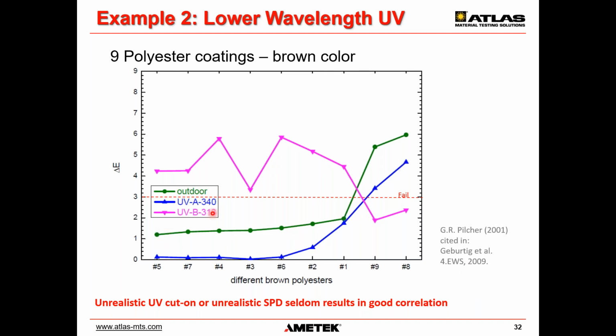The outdoor data is green, the UVA 340 is blue, and the UVB 313, high energy, low wavelength photon UV fluorescent lamps, is in violet here, in pink. And now look at the data. Only coating number 1 produces the same magnitude of change. The UVB 313 lamps in pink produces completely different rankings and magnitudes. The 2 worst performing coatings in the outdoor, these 2 here, they are actually the best in the UVB 313 test. These 2, that's not good.